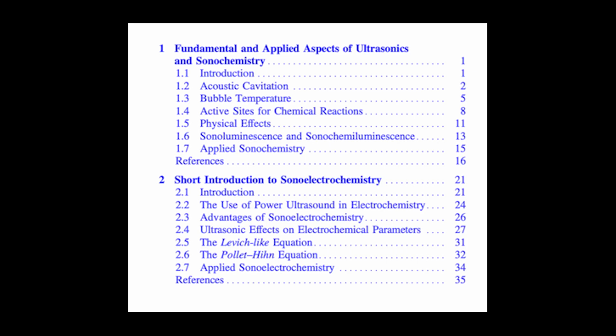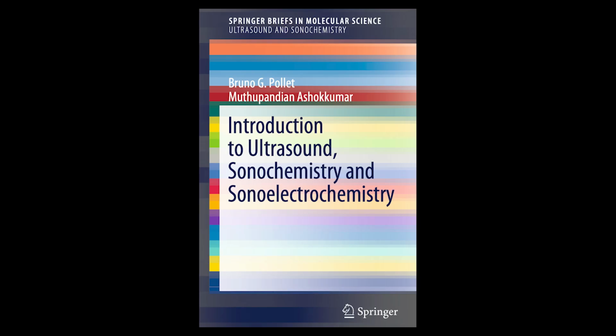Wow, okay, let that sink in. 5,000 degrees, 1,500 atmospheres, created just by sound waves collapsing a microscopic bubble, while the water in the beaker is still at room temperature. That's the magic and the power of sonochemistry — non-thermal chemistry on a macro scale, driven by these incredibly intense but very localized and very brief thermal spikes.